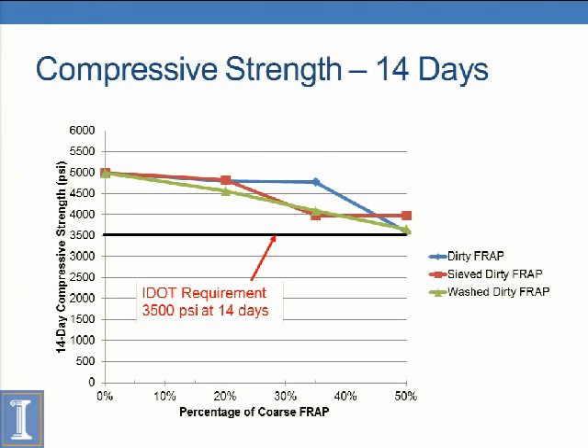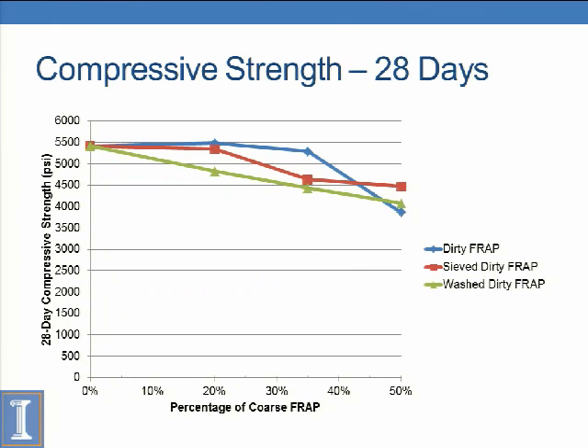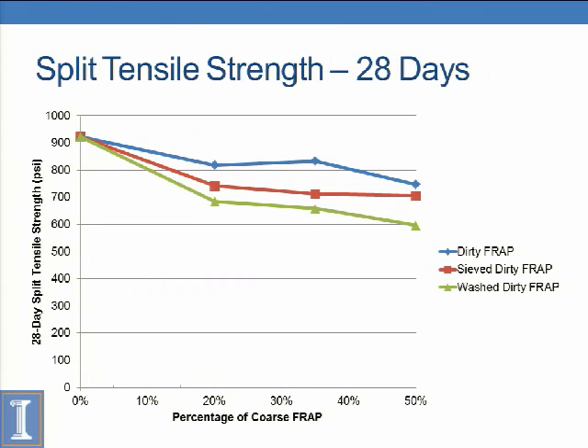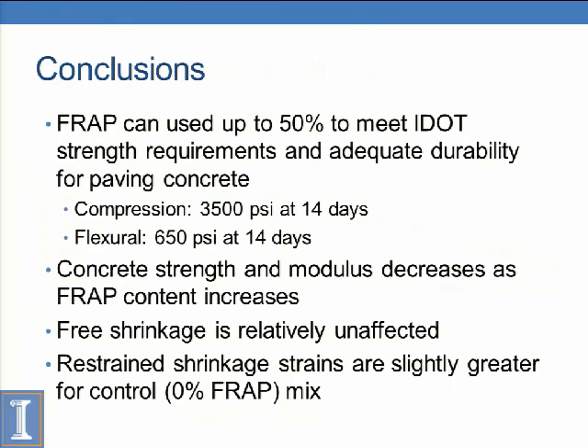IDOT requirement of 3,500 PSI at 14 days again. We can see that all of our mixes passed, even at 50%. This is compressive strength at 28 days. We have an increase in strength as expected. Same with split tensile strength. It's consistent with our previous findings that the split tensile strength will decrease with added FRAP. Also, we can see that the washed and sieved, after we remove those fines, reduces the strength even more. So really, we should just probably keep the fines in there.